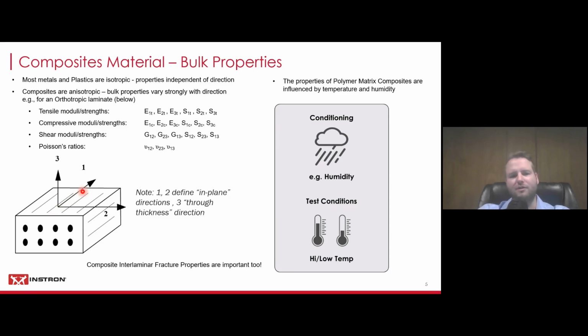So the compressive strength of a composite is typically dependent on how well the matrix material can prevent the fibers from buckling. So you're still going to have quite a bit of strength in compression, but it will typically be much lower than tensile, about a third. But it really depends on the fiber orientation and the different materials that you're using to make your composite. And then in shear, you need to test all the different combinations of directions as well as the modulus determination in those. And then the same is true for Poisson's ratio of composites.